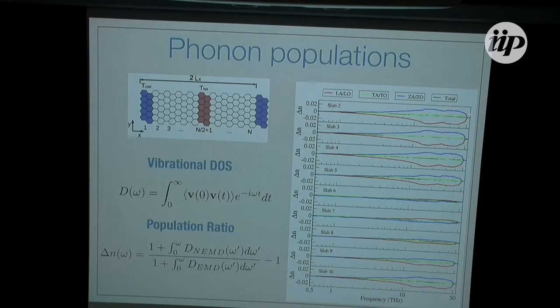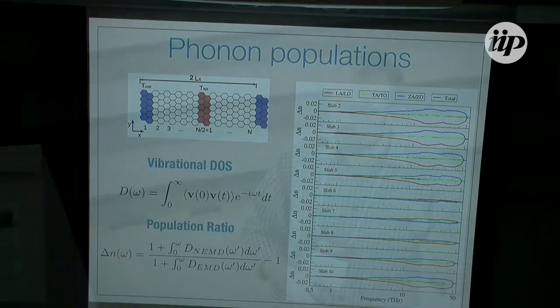So we have an increase in the population of these flexural modes and a decrease in the longitudinal modes. Now, this is really not proof of anything, but it's just showing us that when you have these non-equilibrium conditions, it changes your phonon population throughout the system, and then you wouldn't really expect the equilibrium results to give you the right answer. That was our conclusion, right?